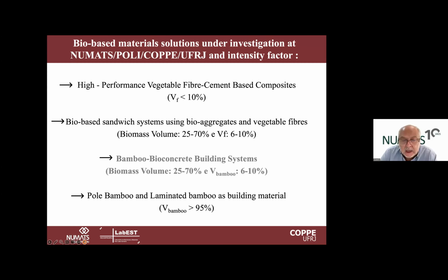And in terms of bamboo, I'm going to show you here today more a system that we are developing now, that is the use of a strip of bamboo reinforcing this bioconcrete. This system, again, becomes feasible because the bioconcrete, as we use much biomass, the elastic modulus of this bioconcrete is in the range of 2 gigapascal. And the typical elastic modulus of bamboo strips is around 20. So we have, again, a ratio of 10 times more stiffness in the reinforcement. This is more or less the same thing as we have when we think about steel and more ordinary concrete, in this case 210 gigapascal and typically 25 for the elastic modulus of concrete. So this is very promising, and this is the focus of my presentation today.